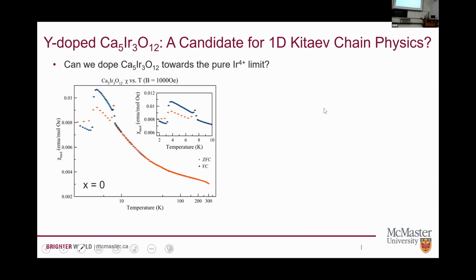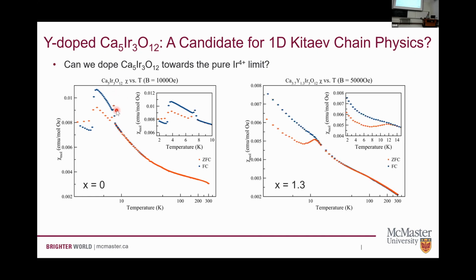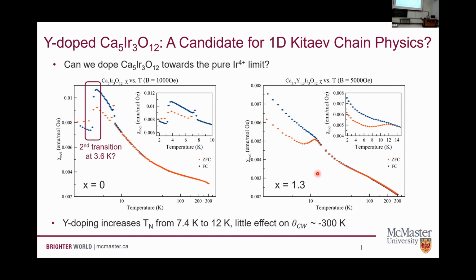We can also look at the magnetic behavior of these materials, and even without getting all the way to our 4+ limit, we can go from the parent compound, which shows this transition at about 7.5, to our highest doped compound, which shows a transition which has been elevated up to about 12 Kelvin. So doping is increasing our magnetic transition temperatures. It's not doing much to our Curie-Weiss temperature, so the overall energy scale for these magnetic interactions doesn't seem to be changing a lot. The other thing that's jumped out here is that we have a previously unreported magnetic transition at lower temperatures that seems to be really robust and reproducible, and also pops up at intermediate doping.